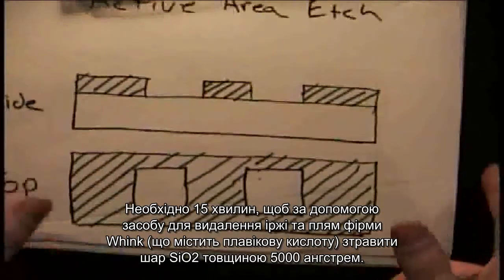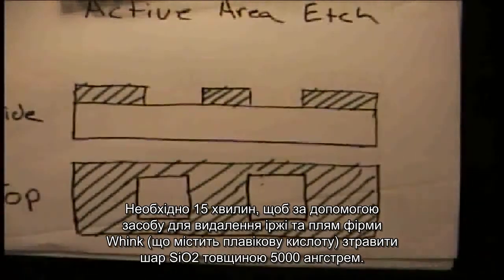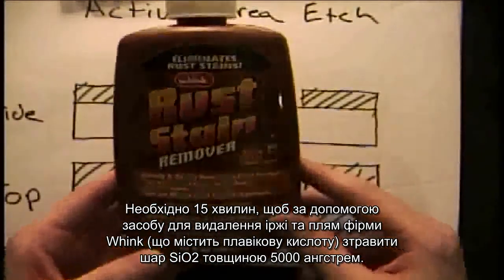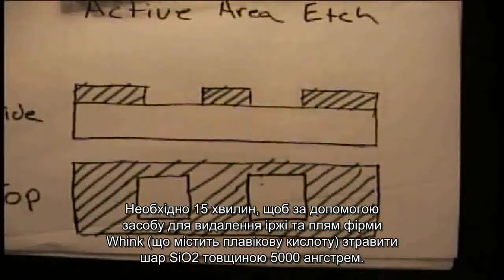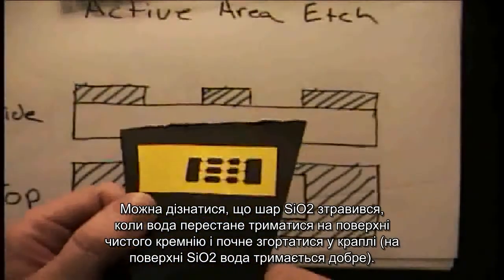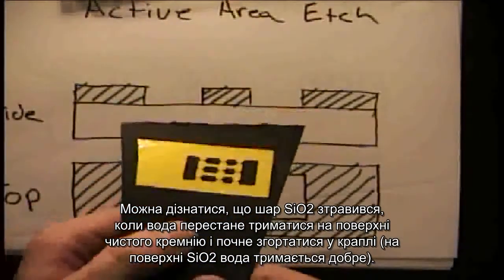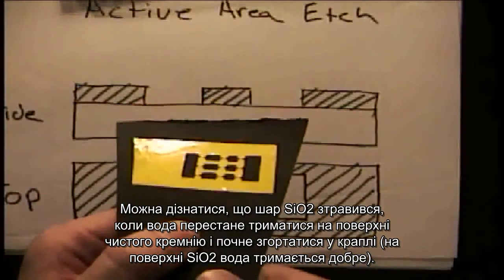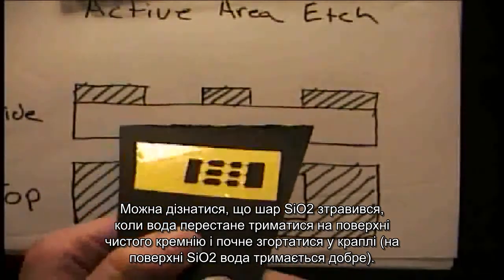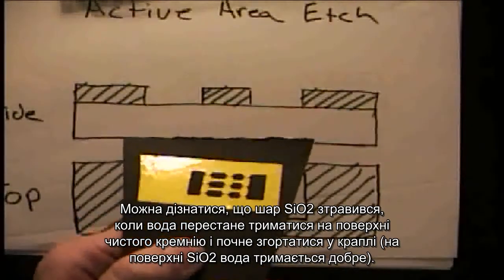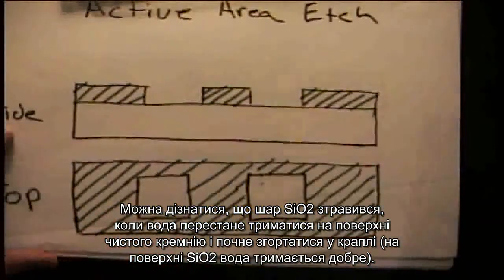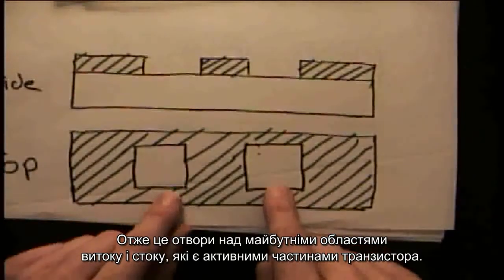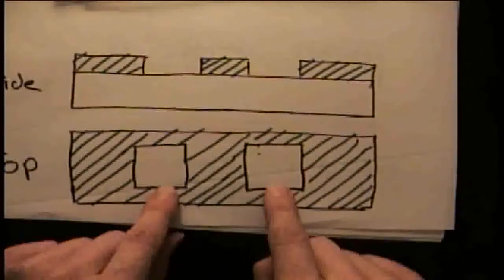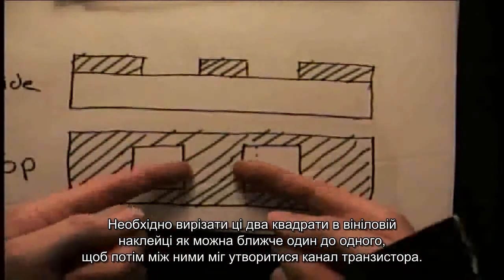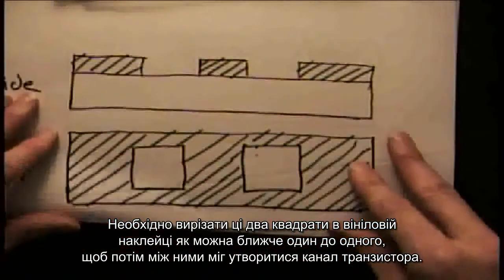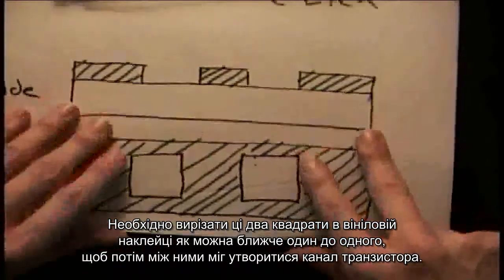It takes about 15 minutes for the Whink rust and stain remover to etch through 5,000 angstroms of oxide. And you can tell when you've etched all the way through is the water will not stick to bare silicon, so it will bead up on the bare silicon, whereas it sticks and wets the oxide layers. So this is the source and drain region that is the active area. So we're going to cut two squares. We're going to try to get in as close as we can to make a channel.